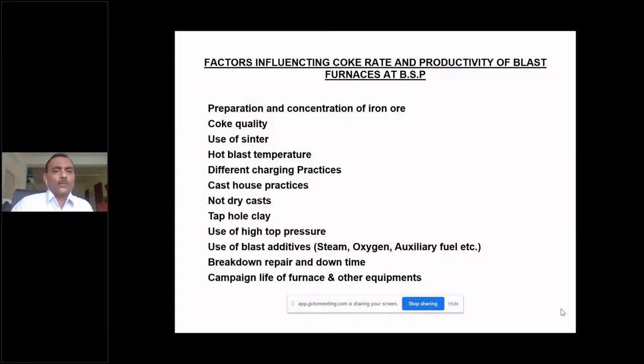As I said, there are so many raw materials we use. Quite naturally, we want the Fe part in our iron bearing material to be good. In our sinter, the Fe part should be good. Coke must have good quality: it should have very good fixed carbon, with low ash percentage. When you use sinter, Fe should be good. When we send hot blast, the temperature should be maximized. Charging practices show how the raw materials are distributed inside the furnace.